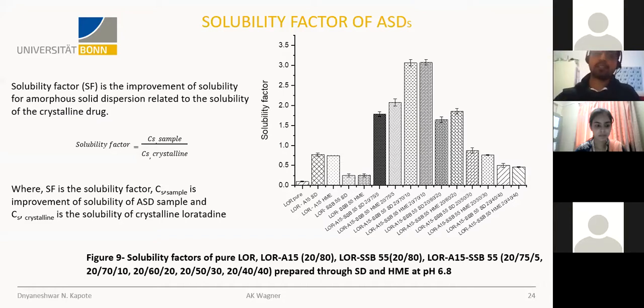20-75-5, the solubility factor was 2, indicating a 2 fold increase, while in case of 20-70-10, the solubility factor was 3, indicating a 30 fold increase in the solubility, which was higher compared with the other ratios. Thus, we can observe here that the solubility enhancement has occurred up to 30 folds, which is quite high compared with the loratadine pure.